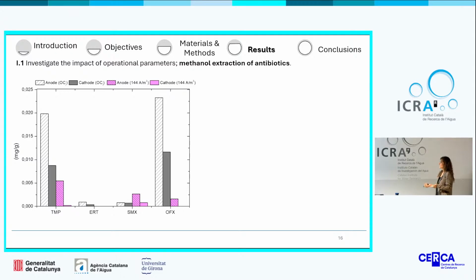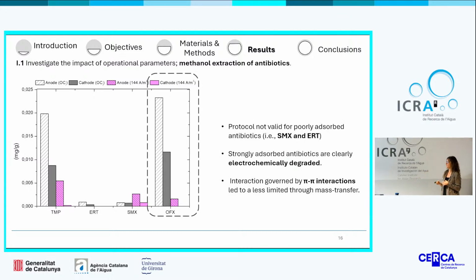To investigate and confirm that we are not only absorbing our antibiotics but also degrading them, the methanol extraction was performed in anode and cathode during the open circuit conditions only, and in anode and cathode when the current was applied. In this graph, we represent the milligrams of antibiotics per gram of electrode. This protocol was only valid for those antibiotics which were highly absorbed onto the sponge, as for example ofloxacin.